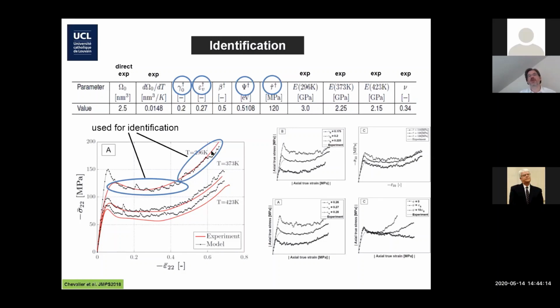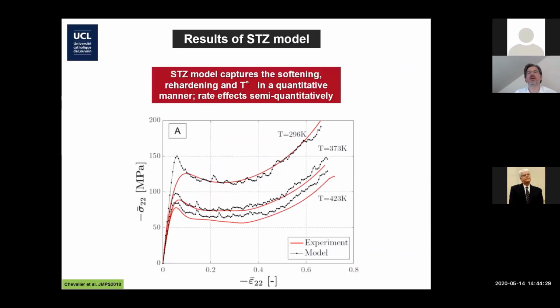So the model does a good job. Just look on the left. The problem is that the model predicts a much larger overshoot peak stress here. I will come back to that. We know where it is coming from, and it will come back. So this is just a larger picture where you see the predictions. Okay, you may say that's okay. It's the minimum we expect from a viscoplastic model for polymers, to capture the temperature.